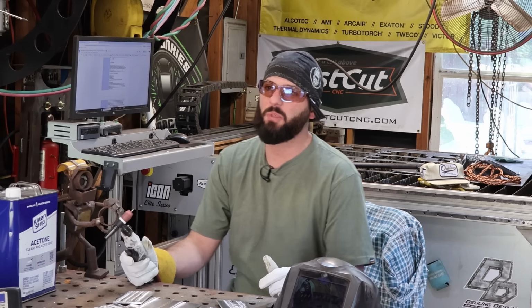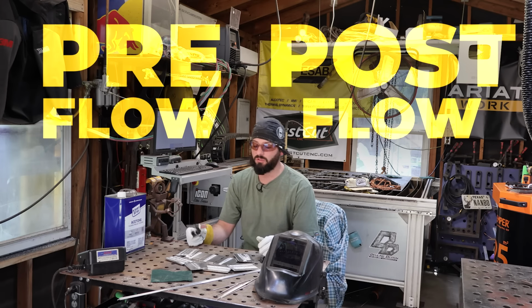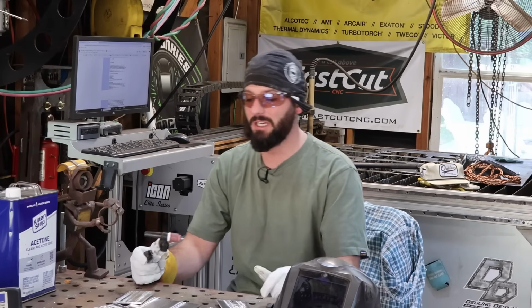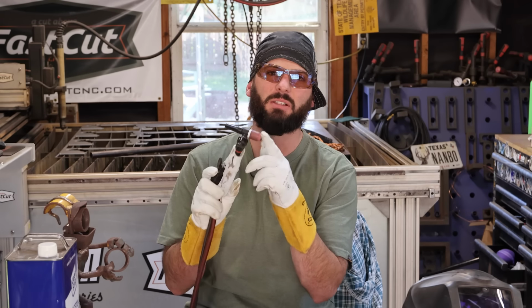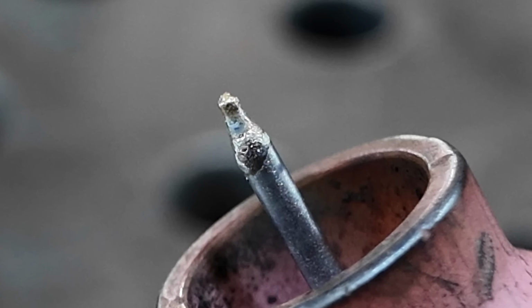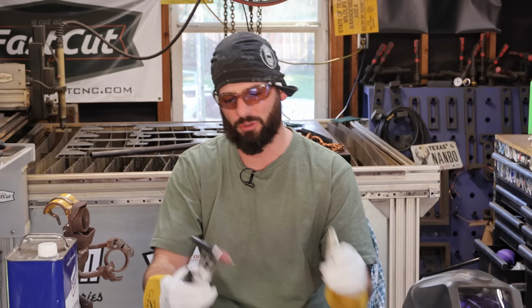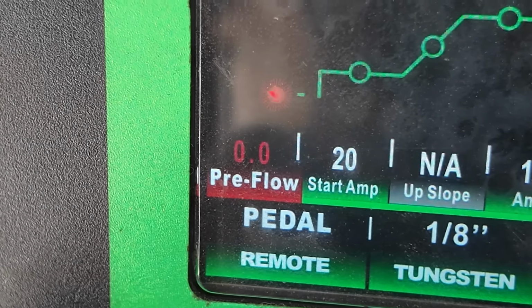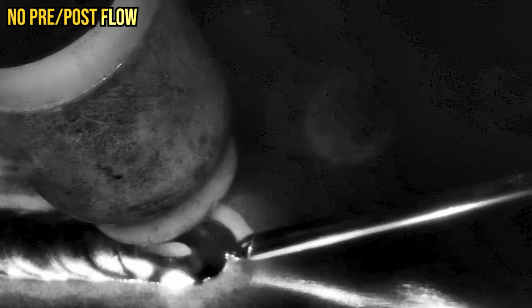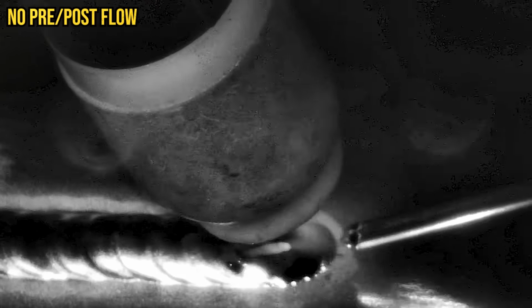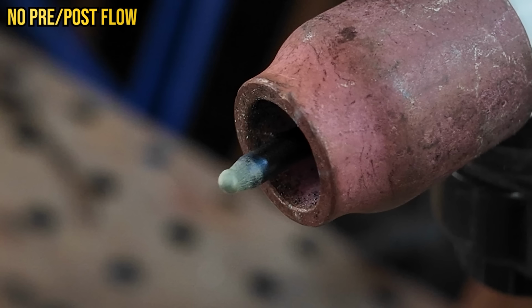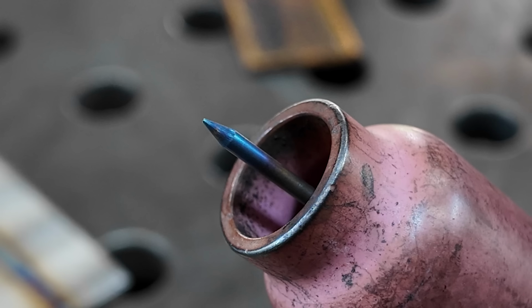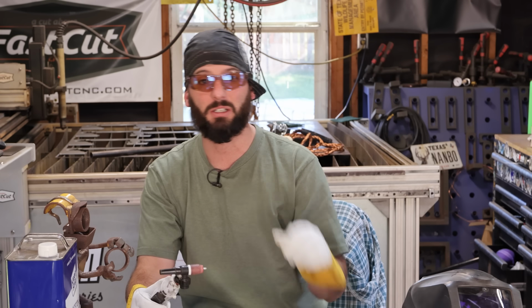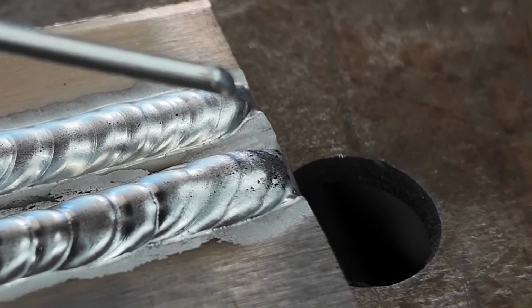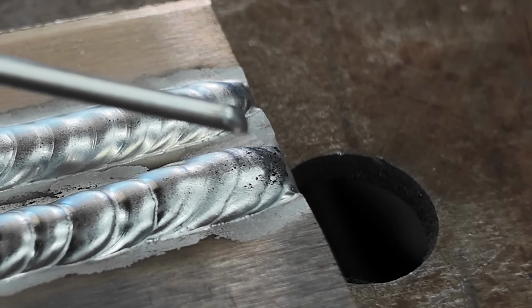The first one I think a lot of people skip, and that's your pre-flow and post-flow. While some people might say it's not necessary, it's super necessary to keep this tungsten clean. If this tungsten is dirty, it's going to put contamination into your base material. So we're going to start there. If you have no pre-flow and just go ahead and turn that post-flow off or low, or you wave your torch around after the weld, you're going to have no coverage on that tungsten, and it's going to get gray, nasty, or maybe a little bit of a blue color. That's going to be those oxides formed on the end of your tungsten. And as soon as you light up for the next weld, boom, you're going to throw all that contamination into the beginning of your weld.